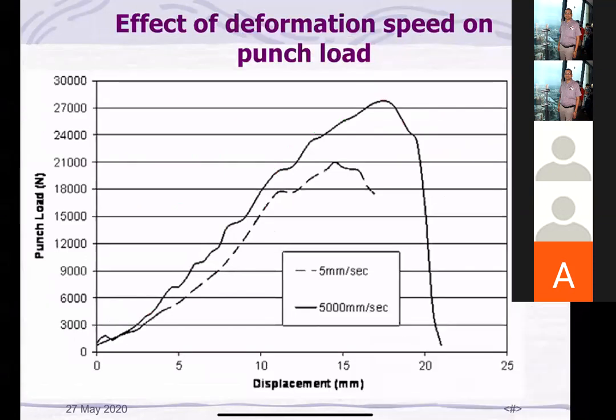Okay? And in the beginning of the presentation, I was telling all of you that deformation speed plays a very, very important role in the simulation, and we should try to use as exact a deformation speed as possible. See, unnecessarily, we should not scale it up. See the load displacement graph for 5 millimeter per second and 5,000 millimeter per second. See, there is a huge difference. So generally what people do all over the world, they scale up the deformation speed by, let us say, 1,000 times, and they try to give the simulation result. Of course, if you don't have the computation capacity, you can do it, but results are not going to be exact. So how to decrease the computation time further?